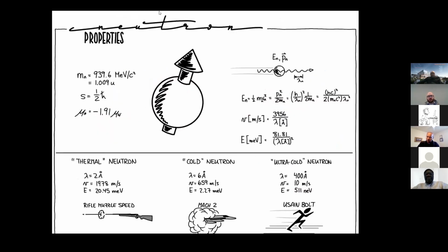Just one quick sketch here as to some of the neutron properties. I just wanted to give you an idea of what the different wavelengths and energies give you. So in the bottom of that, you can see a thermal neutron, which is roughly a 2 angstrom wavelength. It's traveling about 2,000 meters per second. A cold neutron of order 6 angstrom is about 600 meters per second. And an ultra cold neutron is about 400 or 500 angstroms. If you're really fast, you could actually outrun them. And these are all used for probing different phenomena.